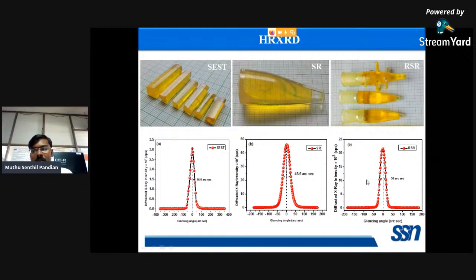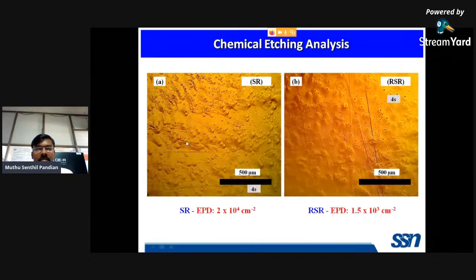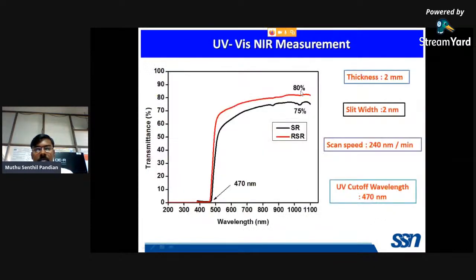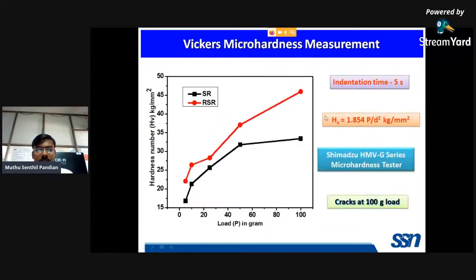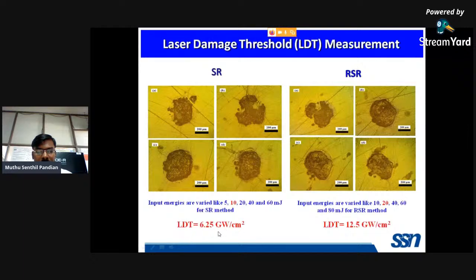Now several crystals we are planning to grow by this RSR method. So this is the chemical etching, this is for SR, this is for RSR. So 2 into 10 power 4 centimeter power minus 2 for the SR method. In the case of the RSR method, it is less. So this is the UV-NIR measurement, 80%, but in the case of the SR method, 75%. This is the Vickers microhardness measurement. So more mechanical stability appeared in the RSR method grown crystal compared to the SR method grown crystals. And this is the laser damage threshold pattern, this is for SR and this is for RSR method.